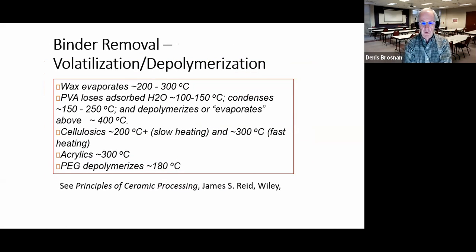So we're going to start with removal of the binder in ceramics. And here, Professor Reid, in his wonderful book, Principles of Ceramic Processing, has given us a chapter which talks about removal of binders, including polyvinyl alcohol, PVA, methyl cellulose, acrylic binders, polyethylene glycol. So many of these things will break apart and depolymerize, break into molecular fragments at certain temperatures, and might depend on fast heating or slow heating. But that's one source of binders. Now remember that binder removal is going to create gaseous species of some sort, which is going to create an internal pressure within the ceramic. And done too fast, that can cause some cracking in the ceramic.